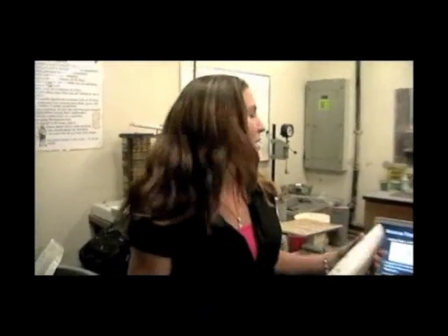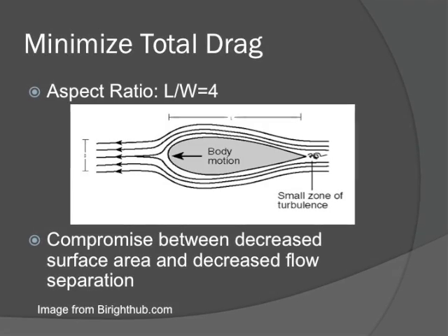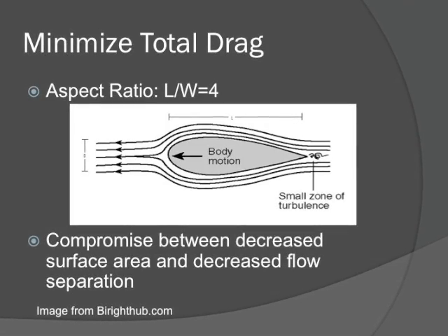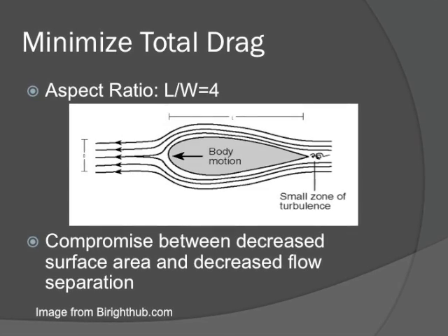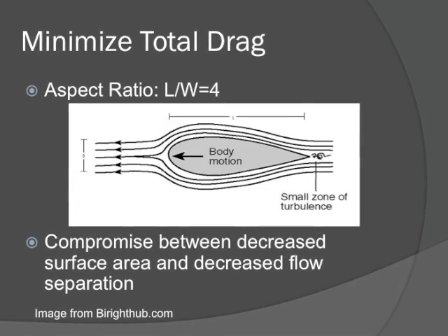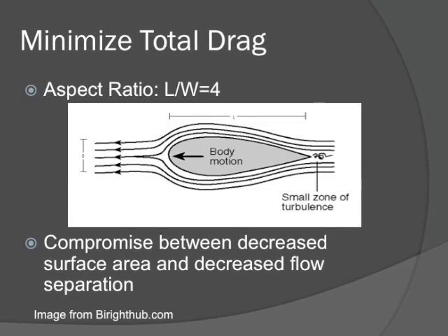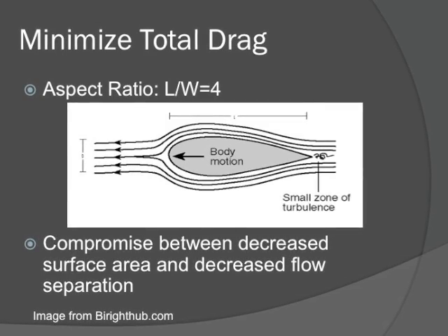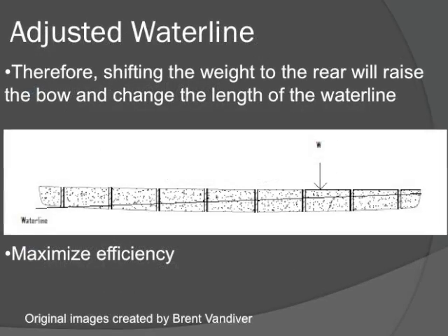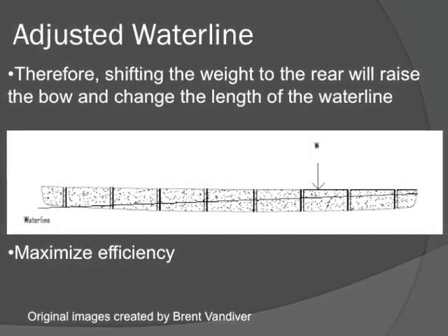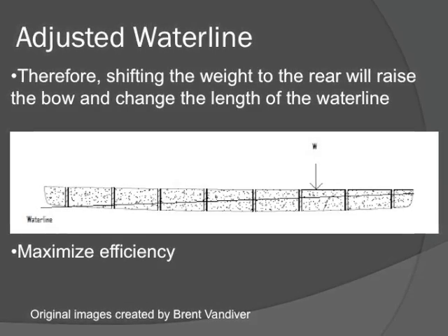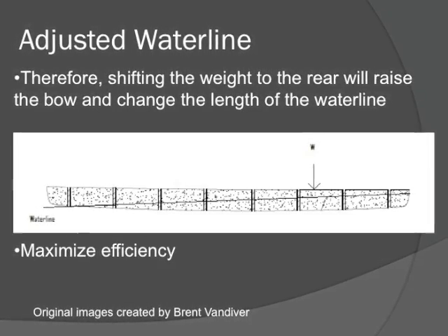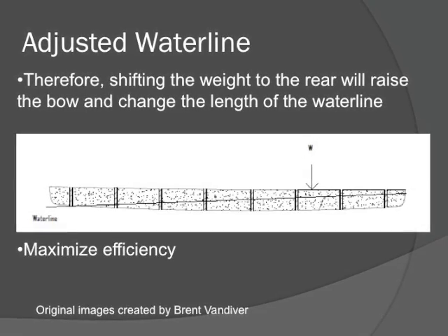In order to get the best chance of winning this canoe race, we need to minimize the total amount of drag force that's placed on the canoe in the water. The way we're going to do that is by using this aspect ratio, which is the length over the width, which should equal approximately 4. It looks to be a good compromise between the decreased surface area and the decreased flow separation. By placing the heavier loads towards the back, the water line is adjusted, essentially adjusting the length of the canoe under the water, which maximizes the efficiency.